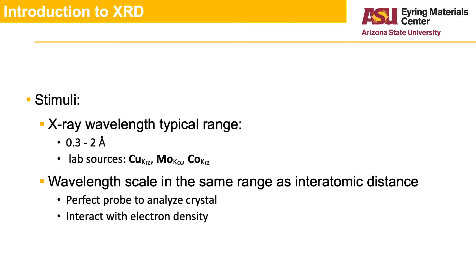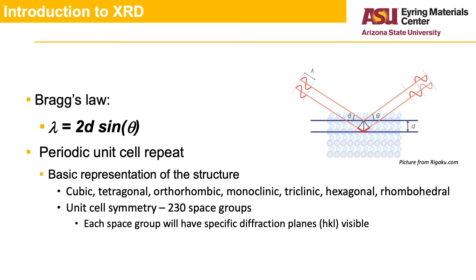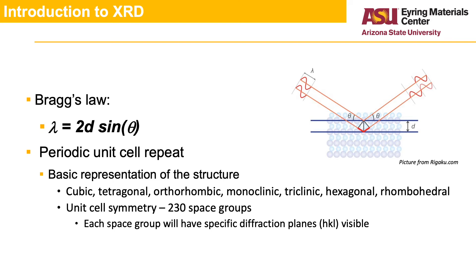The main interaction between the X-rays and the material is with the material's electron density and its electron density distribution. In first approximation, X-ray diffraction is very simple. All you need to remember is one equation, Bragg's law, which is lambda equals 2d sin theta. Lambda is the wavelength, d is the interplanar distance for a set of atomic planes, and theta is half the diffraction angle. X-ray works on the principle of constructive interference, as a result of the infinite repeat of the interatomic distances in a specific direction of the crystal, infinite compared to the wavelength.